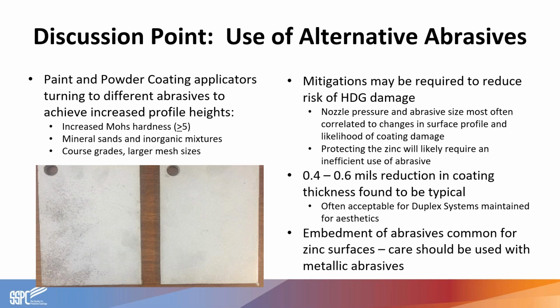We also get asked about the use of metallic abrasives and hot dip galvanizing. We did test embedment, and we did find that with a lot of abrasives, including metallic abrasives like steel grit, embedment tends to be quite common. The zinc is more of a softer surface, the soft pure zinc layer of the galvanized coating. And that may or may not be of significant concern regarding galvanic corrosion, and so that needs to be also addressed by the project. But if you'd like to learn more about the research we've done on the abrasives in preparing galvanizing, do feel free to contact us for more information.